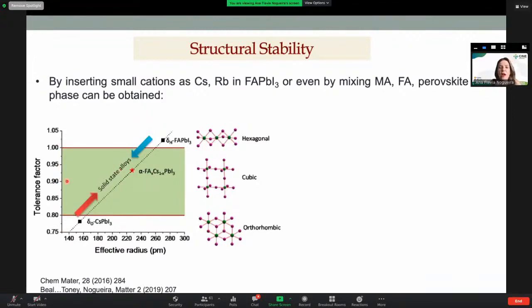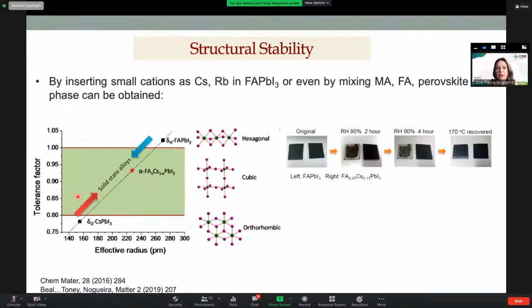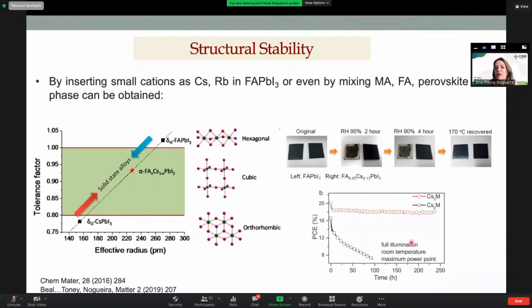So that's the reason we have multi-cation perovskites: by playing with these compositions of cations in the A site, we need to find a tolerance factor between 0.7 and 1. Here is an example of how unstable FAPI is in terms of degradation, but when you have 15% of cesium, you increase the tolerance to degradation. And not only the stability, you also increase the efficiency.